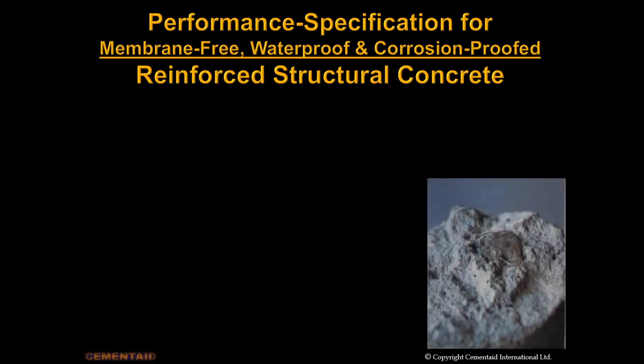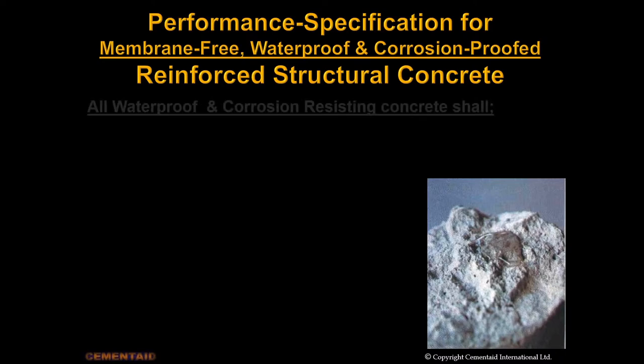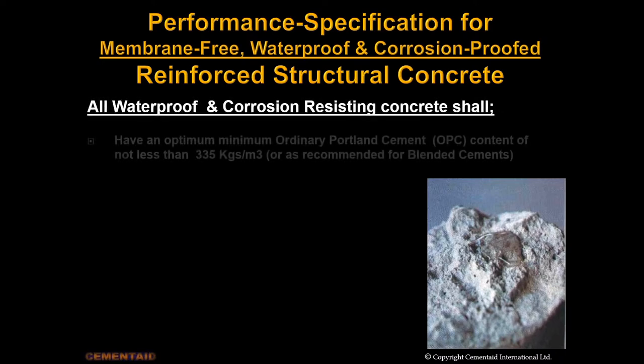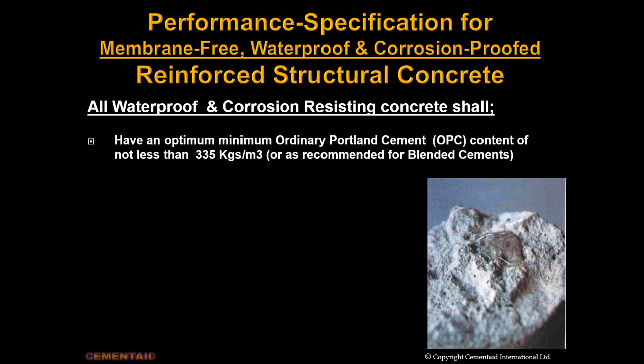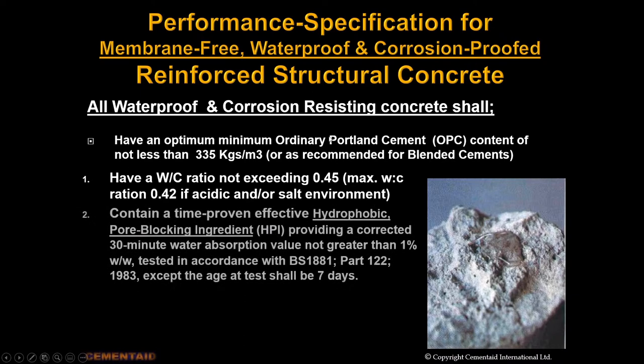A quick look at a performance specification for membrane-free waterproof concrete and corrosion-proof concrete. This is a generally accepted generic performance specification. Cement content shall be no less than 335 kilograms. If you're using blended cements, PFA, blast furnace slag, or silica fume, you can make modifications to that, but this is a straightforward type 1 cement. The water-cement ratio should not exceed 0.45, or 0.42 if it's an acidic or salt environment.